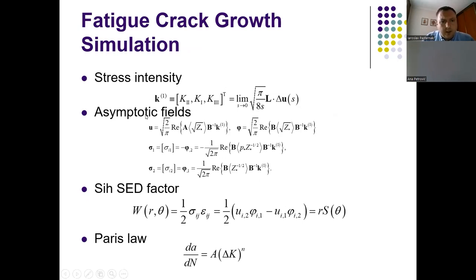For crack development, for crack growth, we use the strain energy density factor and the Paris law, which defined the growth of the crack and the angle of its growth.